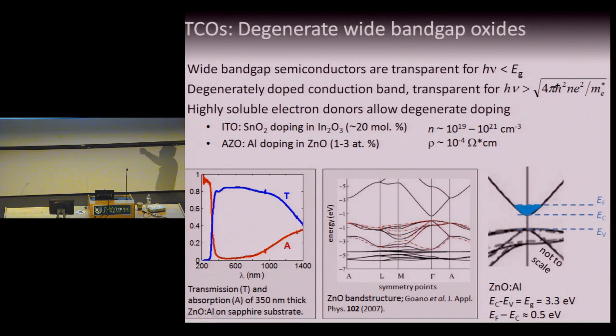In particular, for indium tin oxide, you take indium oxide and dope with tin oxide at about 15 to 20 mole percent ratio. For aluminum-doped zinc oxide, you take zinc oxide and dope with aluminum at about 1 to 3 atomic percent. This gives you carrier densities on the order of 10^19 to 10^21 inverse centimeters, which makes these metals, and resistivities at room temperature on the order of 10^-4 ohm centimeters. To put that in context, that's only a factor of 50 or 100 more resistive than a real metal like aluminum. So these are pretty good conductors, and that's why they're useful for present-day technology.